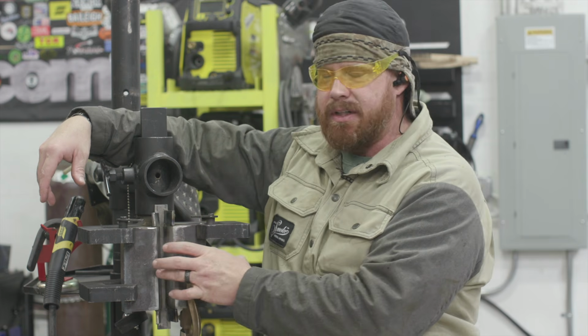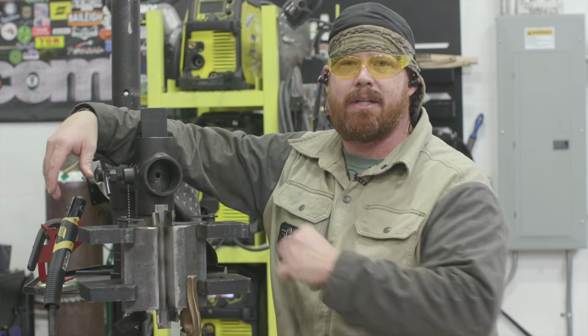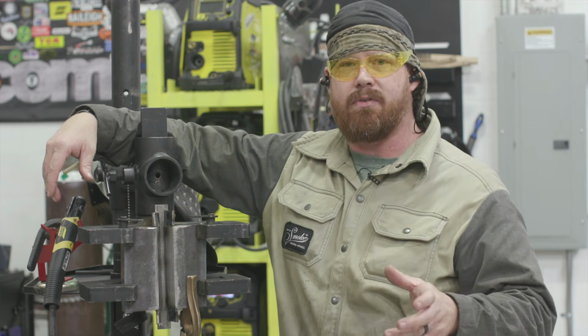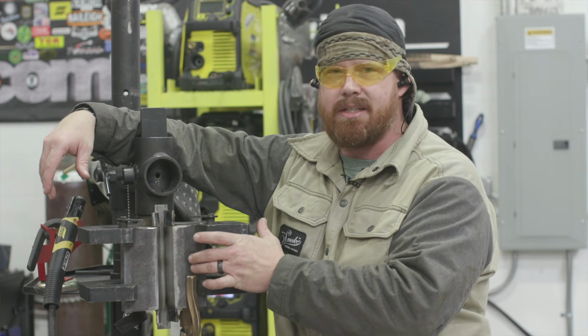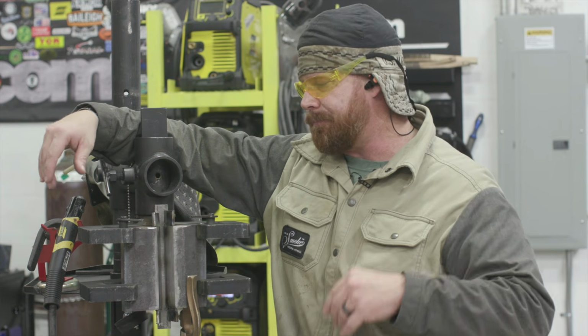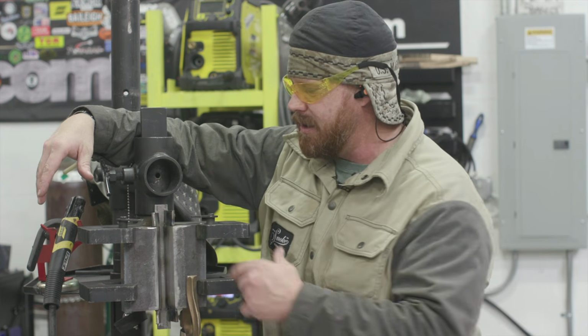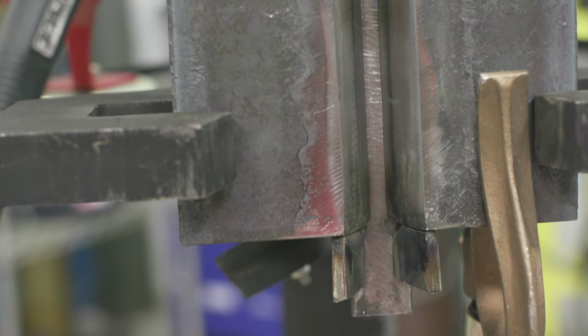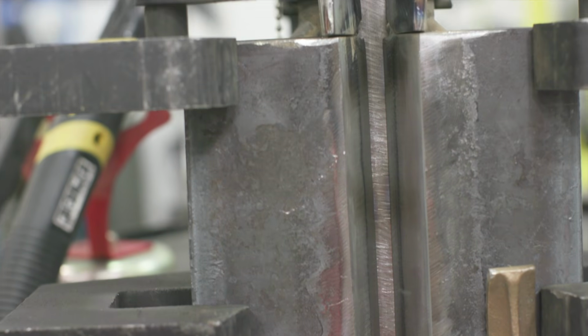So this plate is very similar to, or actually the exact same thing that I did when I had to get my certifications for ironwork. We had to perform a 1-inch test, 3G and 4G. Some of the specs of this test: we have a 1/4-inch root opening. Both plates are beveled at 22.5 degrees for a 45-degree included angle. That means the entire opening of this angle is 45 degrees.